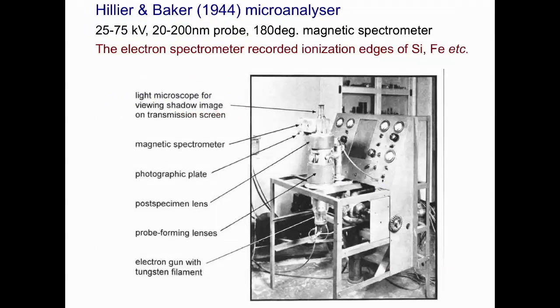The first attempt at elemental analysis with nanometer spatial resolution was made by Hillier and Baker using this electron beam instrument. It had an electron source at the bottom, 3 magnetic lenses to form an electron probe, and an electron spectrometer that formed an energy loss spectrum containing ionization edges whose energy is characteristic of individual elements.